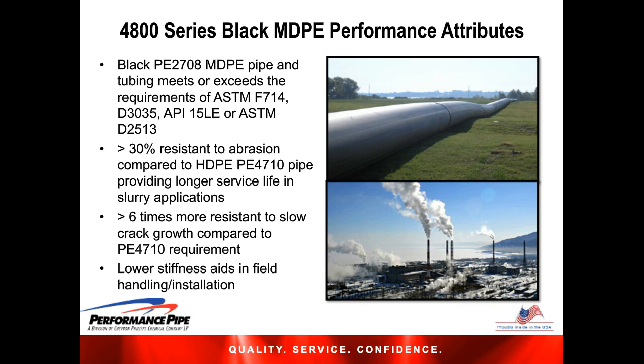We also see this as a potential for customers to be able to use a thinner wall with a PE 2708 pipe while maintaining an equivalent life, resulting in significant cost savings in slurry applications. The pipe is also greater than 6 times more resistant to slow crack growth compared to PE 4710 requirements. Another significant advantage is this pipe has lower stiffness, which aids in field handling, bending, and installation.